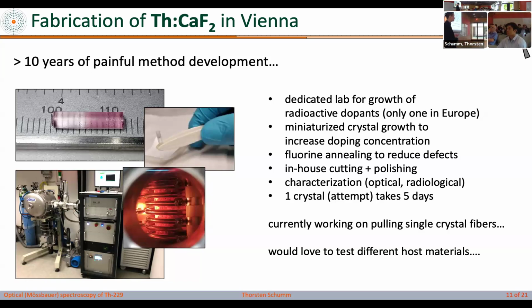I chose it for two reasons. One is it's the most studied, because it's a standard material in UV optics, especially in lithography. In optical mask writers for chip fabrication, every lens, everything is in calcium fluoride. So this is extremely well studied and to some extent understood. And the ionic radius of calcium 2+ and the ionic radius of thorium 4+, which are both the noble gas versions of their respective atom, are almost identical. So if I put thorium into this material, the crystal really doesn't deform very much because the sizes of the ions are almost the same.